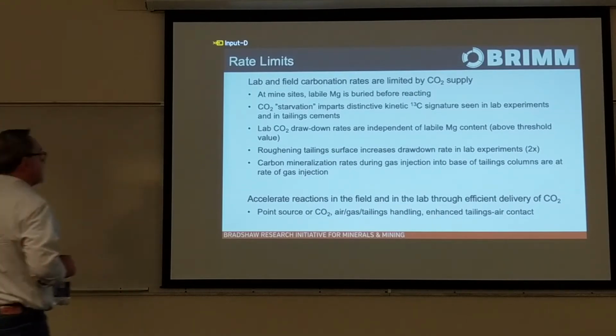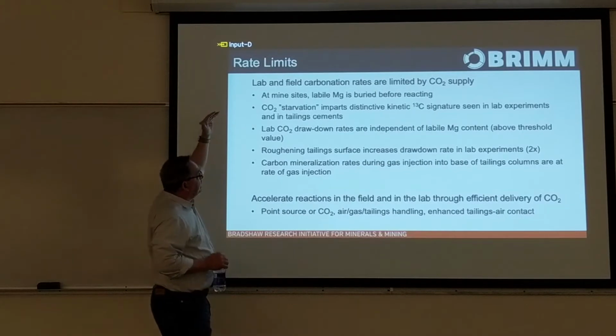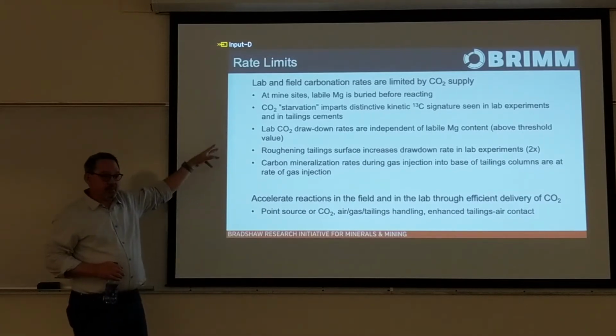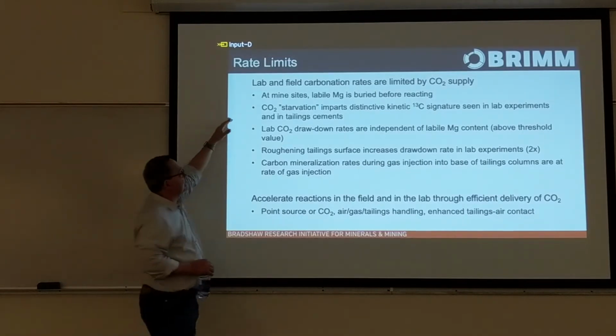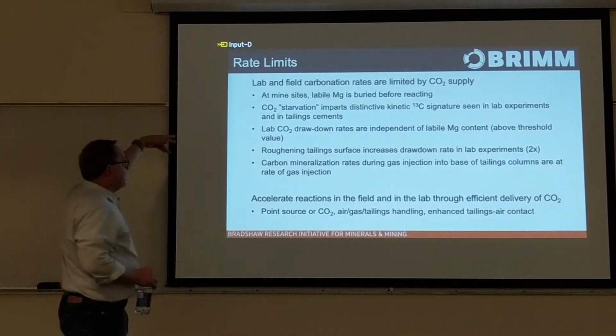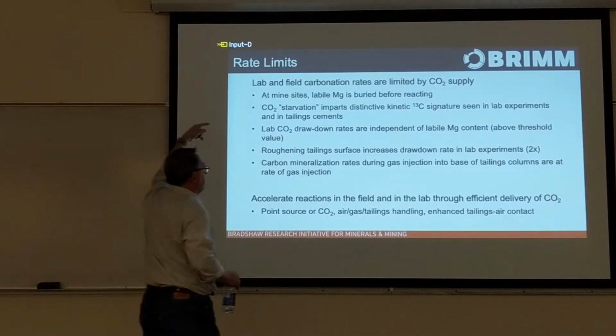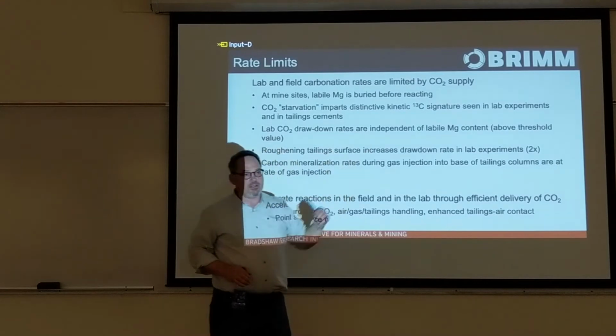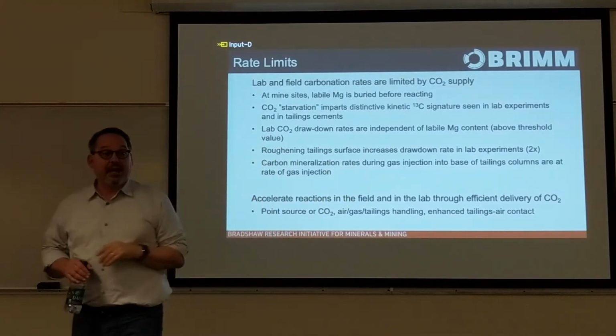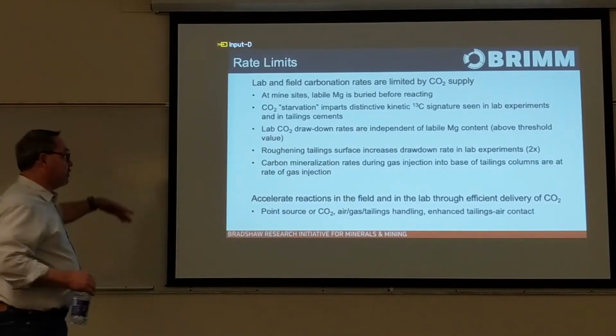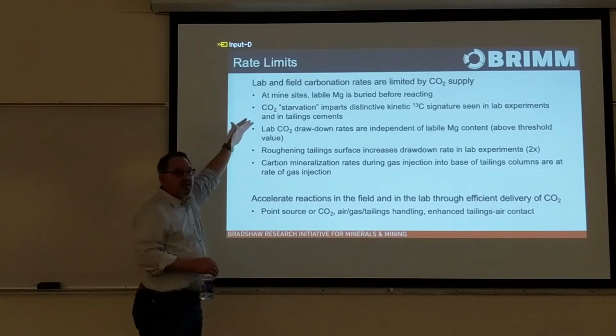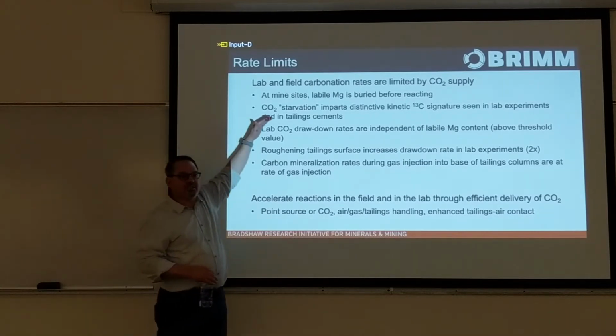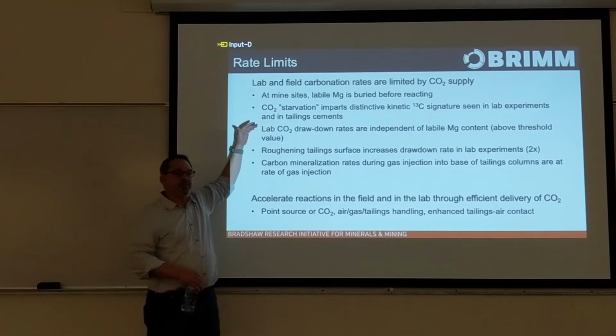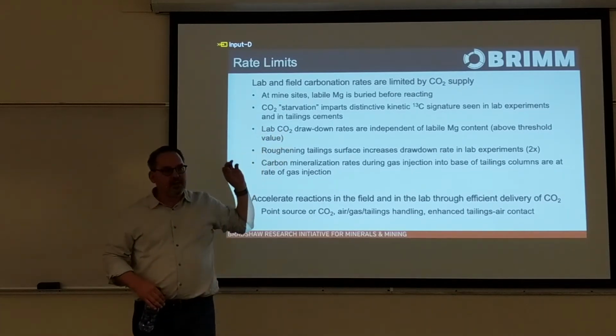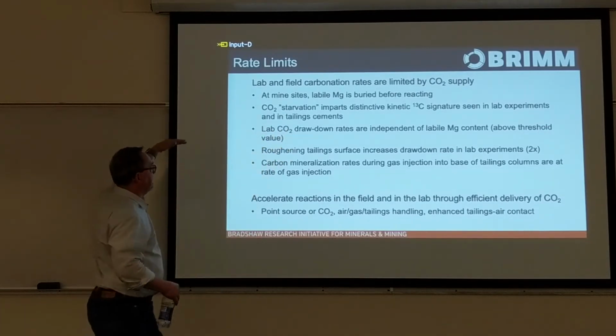So there's a whole bunch of evidence to demonstrate that the carbonation rates that we see in the laboratory and that we see in field studies are limited by CO2 supply. One most obvious one is every mine site we're working at, we bury labile magnesium before it's fully reacted, and you can find it, and we have no measurable CO2 in the pore gas within the first half meter or so. So there's no CO2 getting to depth in the tailings, but there are minerals that are highly reactive. We have labile magnesium and it gets buried.